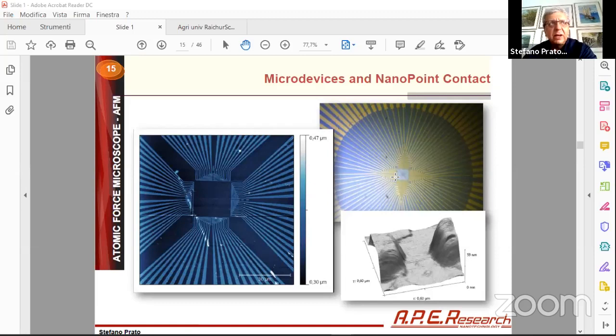Okay. This is very useful if you want to develop, for example, nano sensors. Maybe in agriculture, it is quite popular now to have microsensors, nano sensors, to detect peculiar contamination or concentration of a substance. So if you are in the field of building nanosensors, then you can use a sample like this, where you have very narrow lines here. Those lines you can watch by optical microscope. But if you go to the center, you will see that the color is not yellow anymore. The colors vanish. But it shouldn't, because the material is the same. It's gold all over. But what happened here is that those wires become so small that they are smaller than the diffraction limit. So it's not possible to watch them anymore by optical microscope.